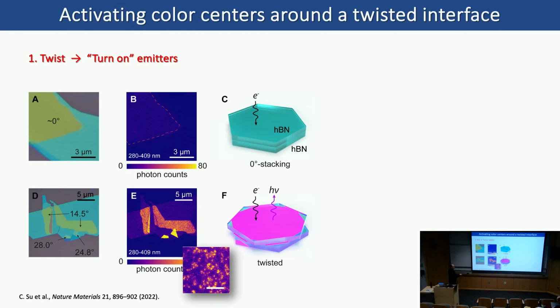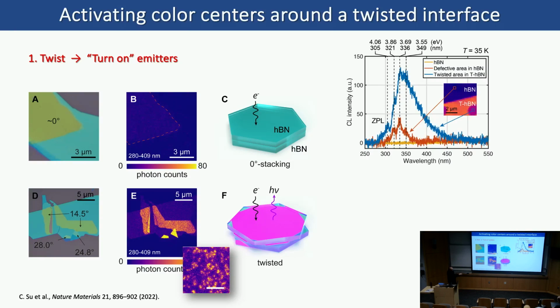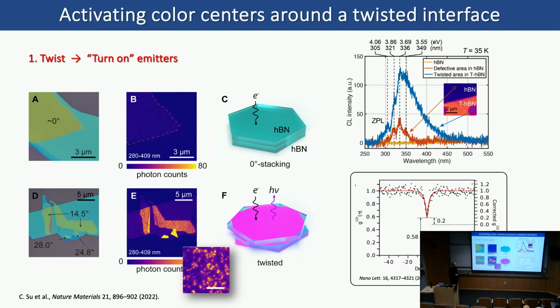And if we zoom in, we still see that those are individual defects. We take the spectrum, and it turns out that this is a very well-known defect. It's called the 4eV defect in hBN. People just give it a name because the zero phonon line is located right at 4eV. Somebody took the G2 measurement, which characterizes its single photon state, whether it emits one photon at a time, and they have proved that this is a single photon emitter.